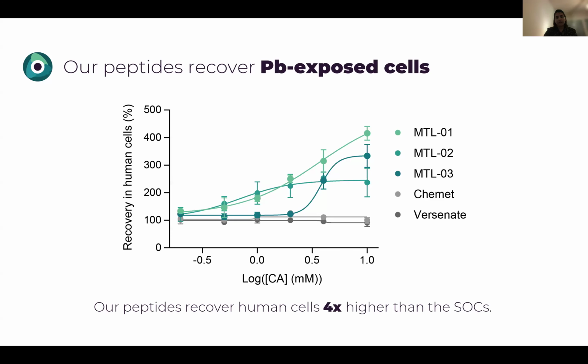have synthesized. In this case, you see in front of you only the 3 best performing peptides, MTL1, 2, and 3. And in gray shades, you see the two standards of care that are used in the clinic to treat lead poisoning. What we've been following after is our ability to recover the cell culture viability at the end of the treatment. And as you can see, those three peptides are superior to the standards of care in recovering the cell culture, up to 4 times better recovery compared to the two drugs that are in the market.